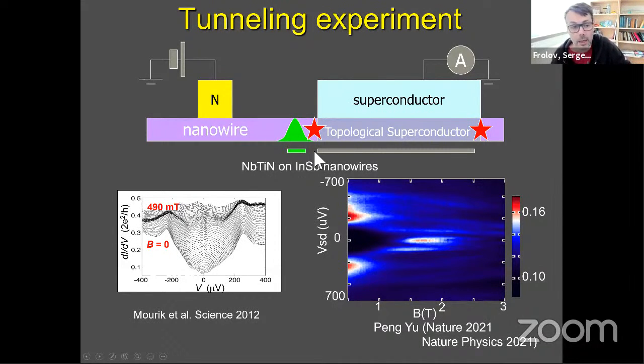Now, underneath the wire, we have electrodes that don't make contact to the wire. We call them gates. So they can change the density of electrons in the wire or a chemical potential. And especially here on the edge, the green gate, we can make it very negative, repel all the electrons from this region and create a tunnel barrier. So then the left side of the device acts as a tunnel probe on the right side of the device.